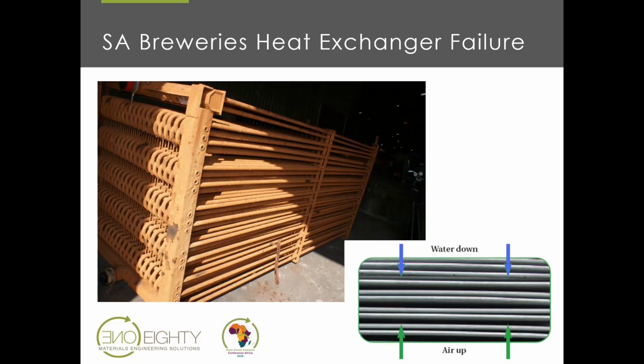So this heat exchanger just kept on leaking, and they took it out of service. They had 8 of these heat exchangers, and these heat exchangers controlled the brewing process. So if they had more than 2 out of circulation, they had to shut down the brewery. All 8 of them looked like this. Okay? So they were now managing which one was leaking more and keeping 6 out of 8 in service.